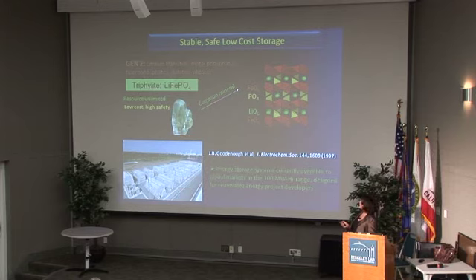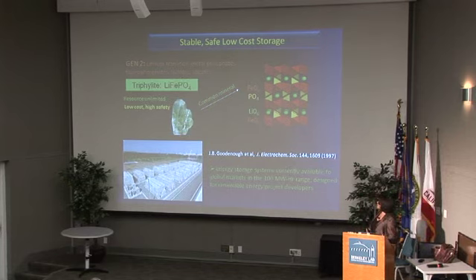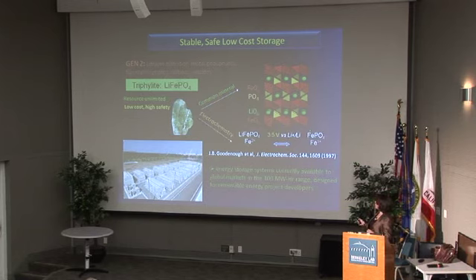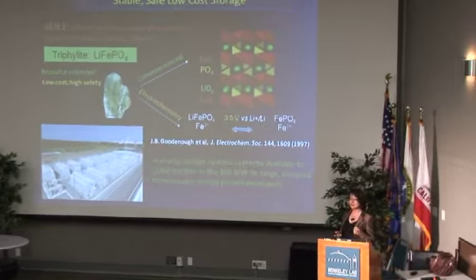So this material called triphylite, lithium iron phosphate, is cheap, low cost. It's resource unlimited. It has high safety. It has all of the right characteristics except for poor conductivity. And it was reported by Goodenough in 1997. And it has been, as I said, the subject of much work since. So it has octahedra of iron oxide with tetrahedral phosphates, lithium ions running down these tunnels. And the reaction can be described as this. All of the lithium effectively can be removed from the material at a potential of about 3.5 volts. And it gives rise to a theoretical capacity of 170, which can effectively be almost realized in practice. Our work on this started in 2000.